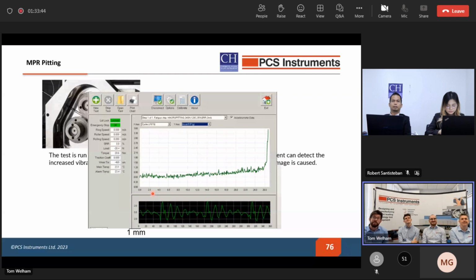You can see that for much of the test, the vibrations are really low. And this is because what we're seeing is just a crack slowly propagating. But as soon as that pit is formed, you get a very large spike of vibration. And what's fantastic about the MPR is you can stop the test as soon as that pit occurs, so no more damage is accumulated after that, which means it's much simpler to analyze the results, analyze these pits that are formed from your pitting test.